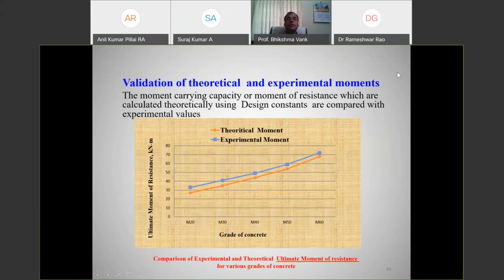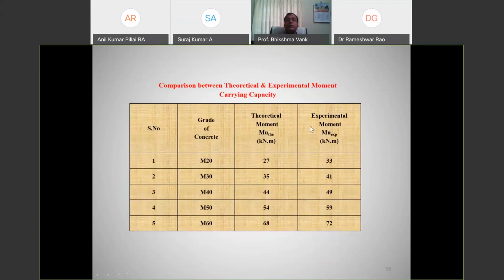Validation of theoretical and experimental moment. The pattern is the same, so experimental moments are more when compared to theoretical moments. It means your investigation shows geopolymer concrete is effective for use in structural grades of concrete, special concrete. Theoretical moments, the experimental moments. Please see here, all these experimental moments are more than the theoretical moments. This is 27, 33, 35, 41, 44, 49, 54, 59, 68, 72.